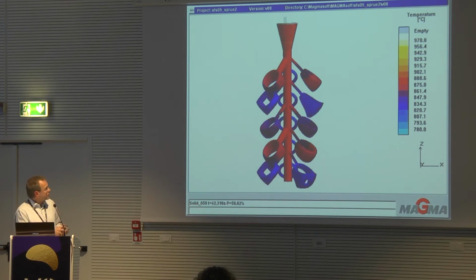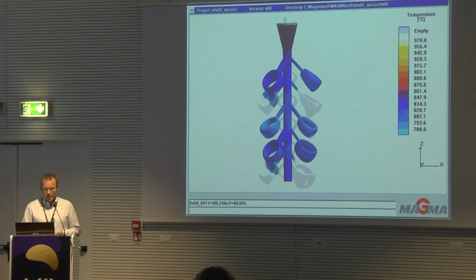Now, just opposite to that, if you have the sprue thicker, bigger, and more positioned on the heavy side of the ring, this will work much better. Solidification will progress in this way, and this will be the best case to avoid shrinkage porosity.